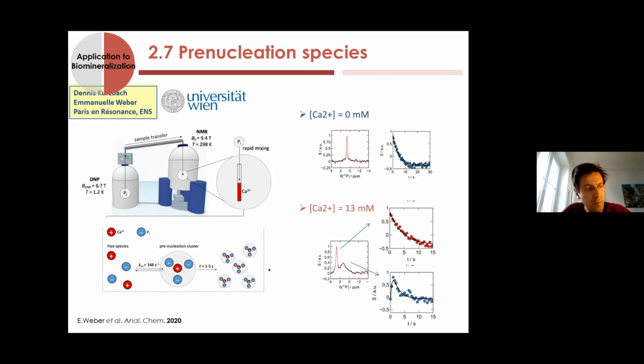Revealing the signal is really challenging because the formation and nucleation of a calcium phosphate phase is extremely quick. When you mix a calcium solution with a phosphate solution at the right pH, around 7, the precipitation is almost immediate. So that's really a challenge.